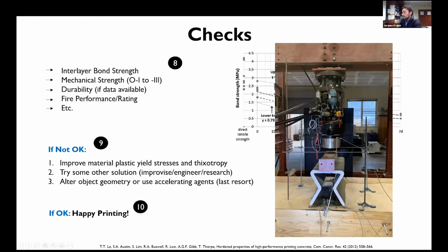As an example, I think it was a year or 2 ago, we did an X-bench project with two of our PhD students. We printed this bench. I think it's about 1 meter in length. And we applied a load with our Instron actuator on this transfer beam. Surprisingly, for a thin-walled concrete element, I think it's about 30 or 40 millimeters thick, this bench could sustain a load of 3 tons, where we didn't even get brittle failure because we added polyprop fibers. So it was just starting to crack. So if you design correctly, you can really get strong structures, even though you have interlayers.